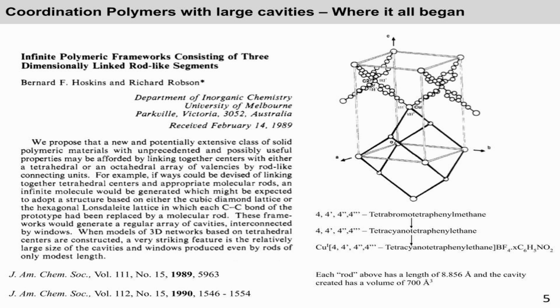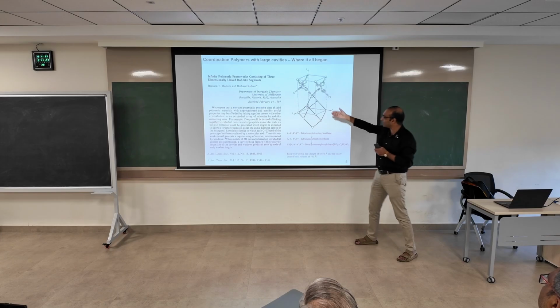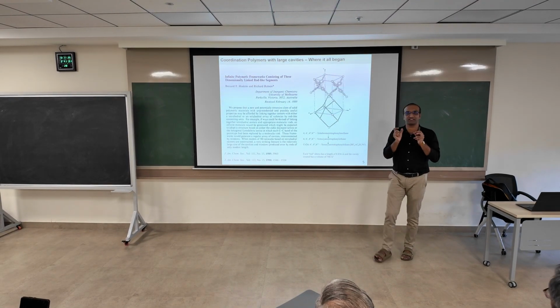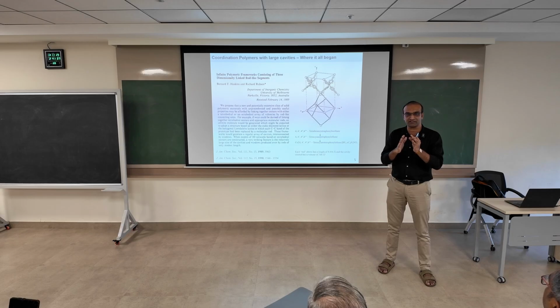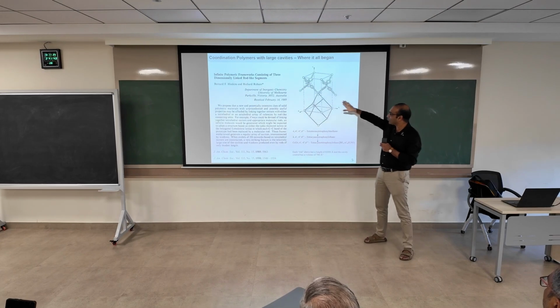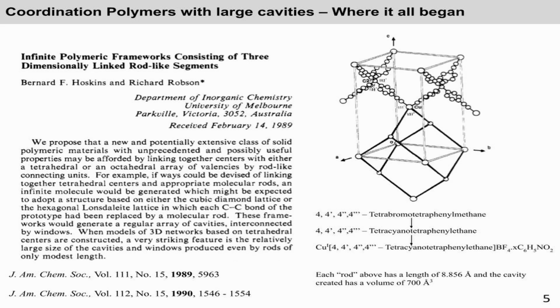Normally when these solids form, they form interconnectedly, and they don't have a gap in between. Like earlier when they were trying to make these compounds with zinc cyanide and copper cyanide, what would happen is you would have these adamantane cages of zinc and cyanide interconnecting with each other, interlinking with each other and leaving no space. But this is the first time when he made it, he got this huge void. There were portions where there was nothing there. There was volume to fill it with.